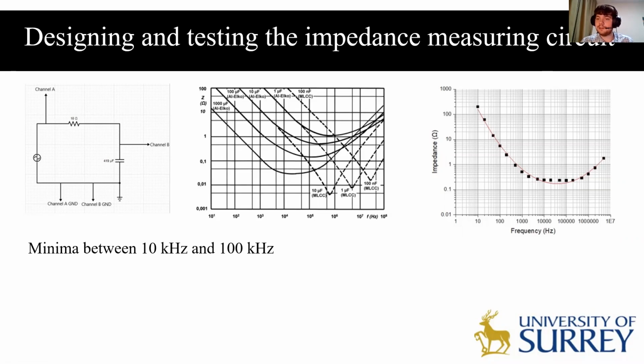Also, I found that the turning point was indeed between 10 kilohertz and 100 kilohertz, suggesting that my initial hypothesis was correct. This demonstrates that my circuit is indeed capable of measuring the frequency response of a component, and I can use this circuit further to test other components.